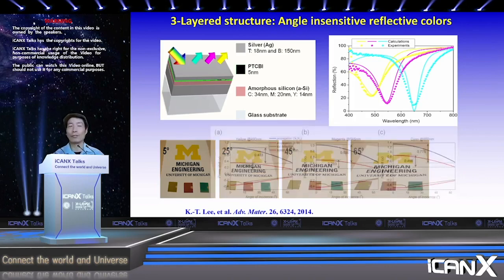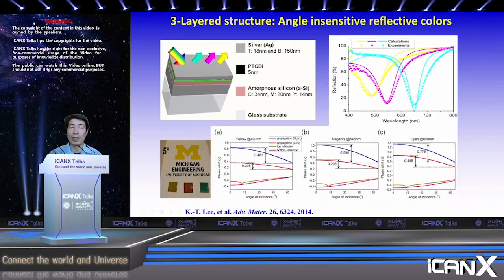So that if you break into pigments, it still looks the same color, doesn't matter which angle. So this can actually give rise to this angle independence. Even though the light propagation in this layer, of course, depends on the angle, the light reflection from the interface of the silver and the amorphous silicon also has an angle dependence. And they happen to sum up to basically zero, okay? So that's also multiple integers of 2 pi. So that makes angle independence. It's a very interesting effect, put in a practical use, okay?